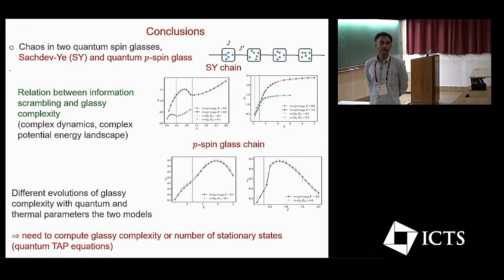Yes. In the actual system, you can tune it in different ways. Basically, it's an angular momentum scale, so you can tune it by tuning some temperature scale, effectively the kinetic energy. You change the scale of momentum and position, and you can tune it. Right, it's finite temperature. So this general phase diagram that I showed earlier, let me not go back into it because it will take some time. The general phase diagram you can study at zero temperature, and you can just go across the h-bar. That will be a quantum transition. These models all have a quantum phase transition, and there also you see some features, although it is most interesting in the thermal case where you have this complex dynamics.